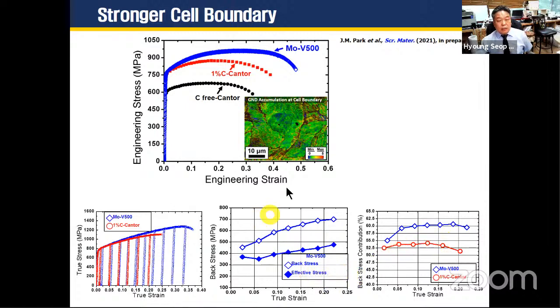So we can see this in this EBSD here. GND, geometrically necessary dislocation, is the blue and yellow color in this EBSD, and these GNDs reside near cell walls in TKD. It's not shown here, but transmission Kikuchi diffraction analysis can show much smaller. This is a TEM-based one, much smaller geometrically necessary dislocation like this.